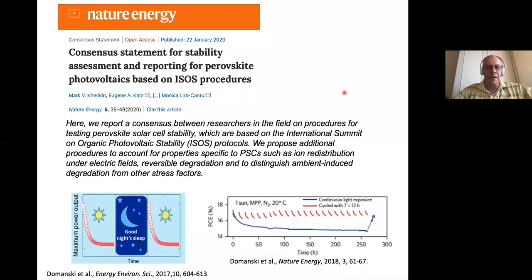One of the peculiar effects which deserves also fundamental research is, as I said, if you start to do your solar cell efficiency measurement here, you decrease maybe 5-10% of your power output, you let the solar cell rest, you switch it off, maybe overnight, and then in the morning you are back again at the same efficiency. So there is a reversible decrease here, which jumps back when you switch it off. So that raises the question of how to do stability testing. If you just follow the power output under continuous light, you may feel that, okay, it's degrading here. But if you do chopped light, 6 hours difference, it looks very stable. So that's one of the things which needs to be understood and also to be taken into account for stability testing.